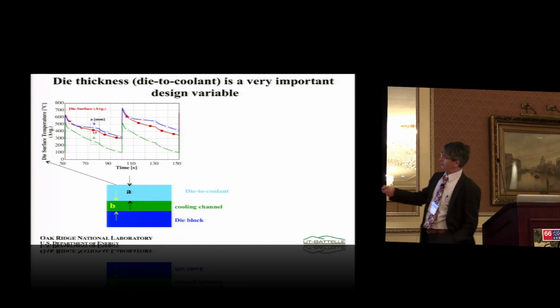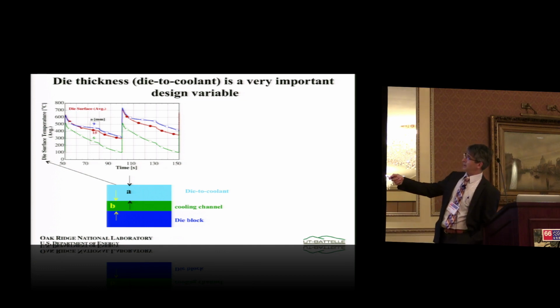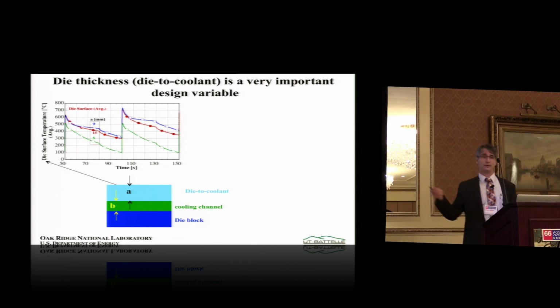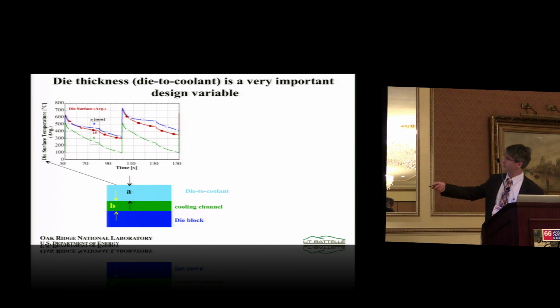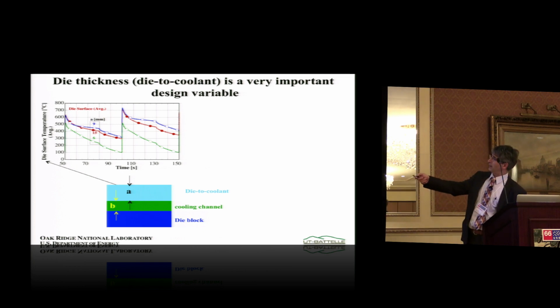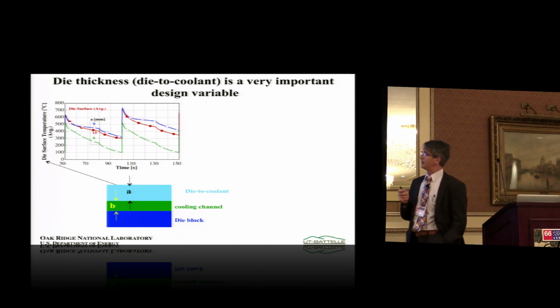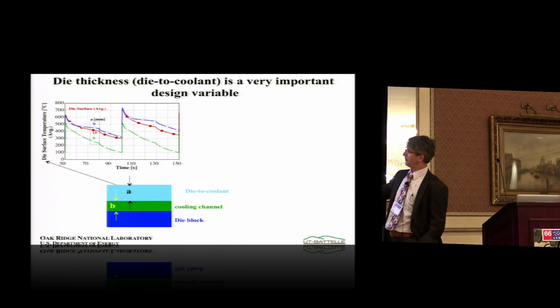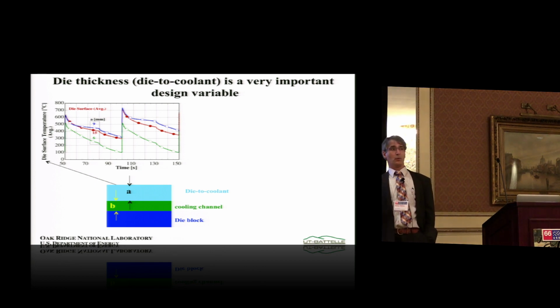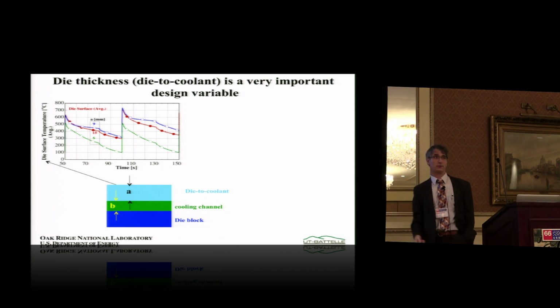So more data here. If we look at the die surface temperature, we identify that this parameter right here, we call it A, die-to-coolant thickness, is very important because you can overheat the die in cases where this dimension is too thick. So the take-home point here is not only that the cooling is important. It's important where that surface is placed. Is it going to be up close to the die, or is it going to be away? We know that if it's going to be away from the surface, it's not going to be efficient.